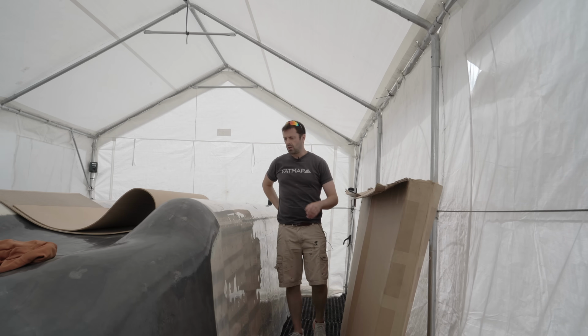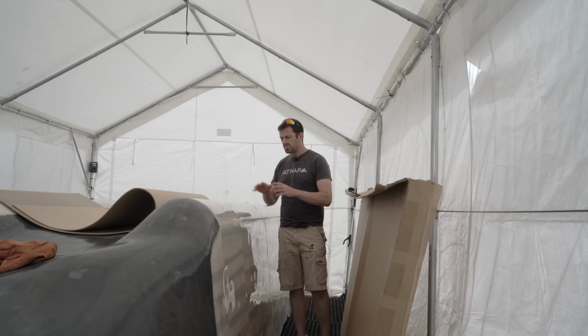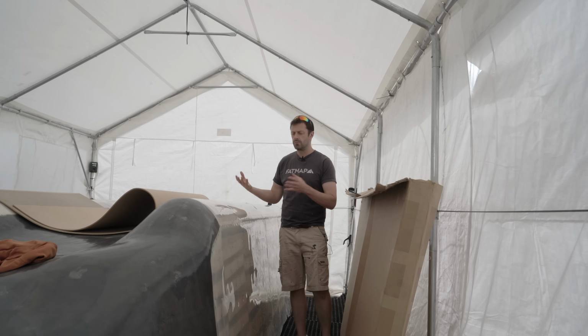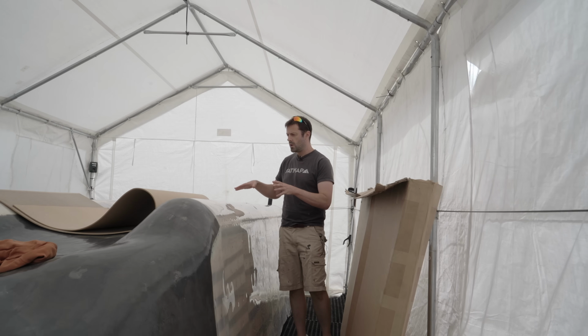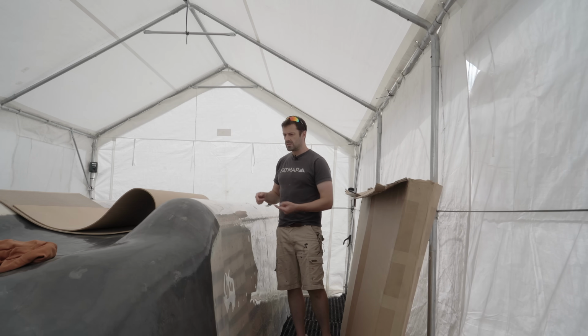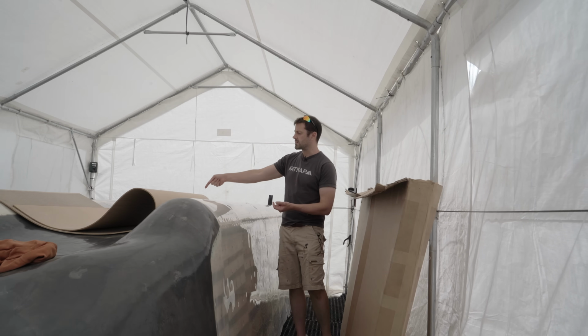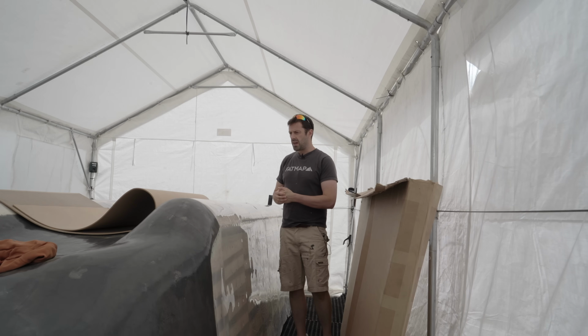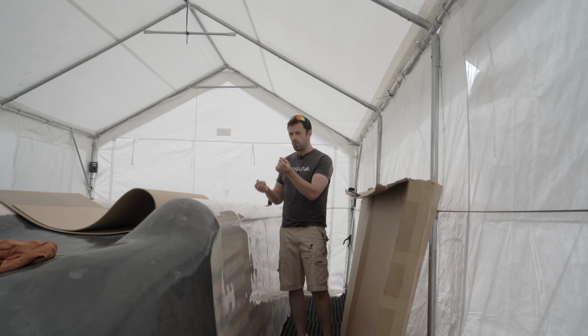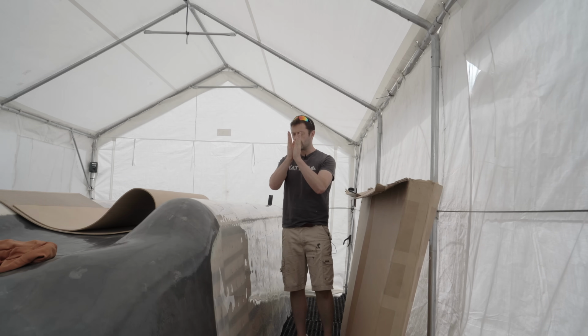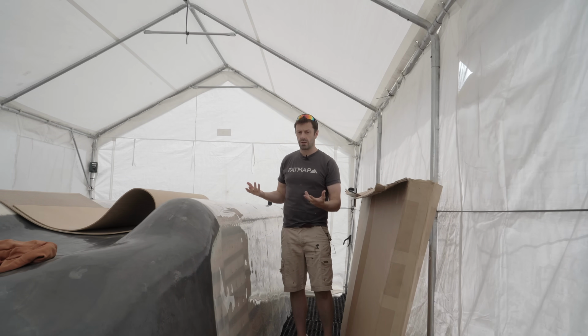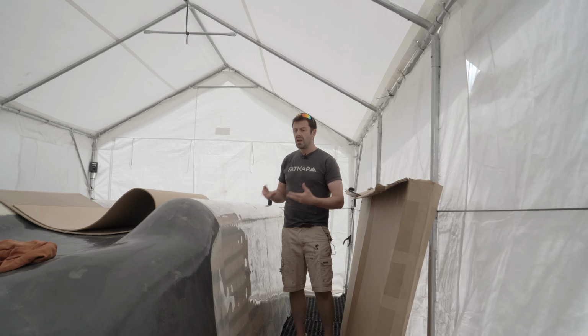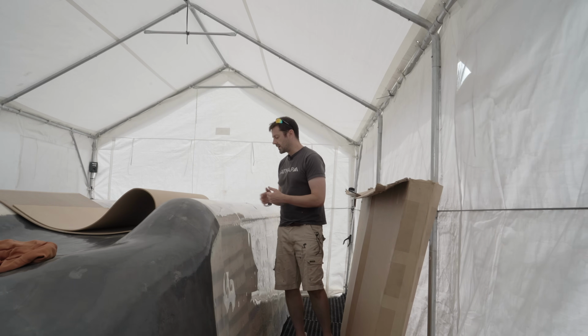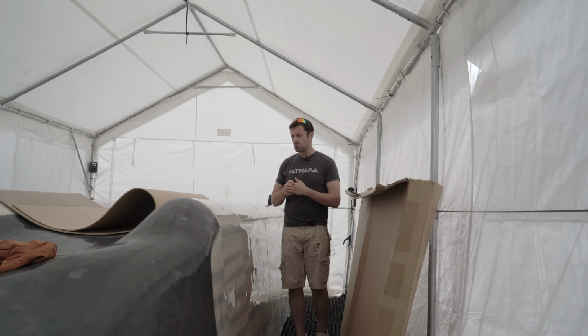There are lots of ways of turning foam into a shape that conforms either 2D or 3D with a part. One way is to actually score it rather similarly to this MDF, and then of course you'll end up with air voids in those little V shapes as it goes around the corner, which you then have to fill with something, or you might even leave them as a void. You might fill them with resin, whatever. It can actually end up adding quite a lot of weight to your part.